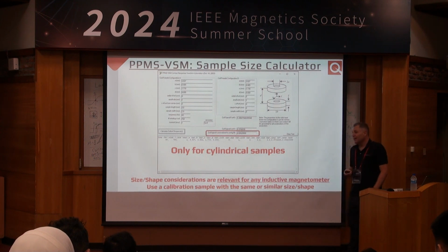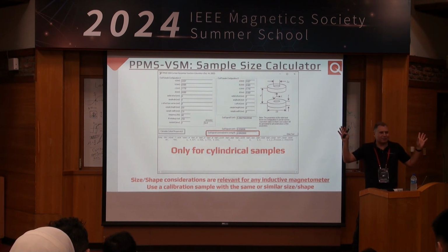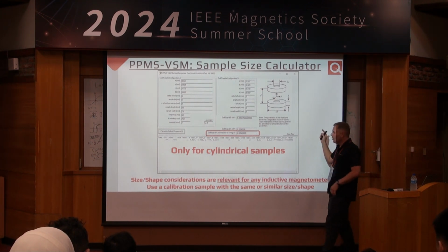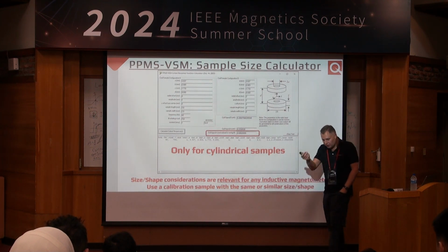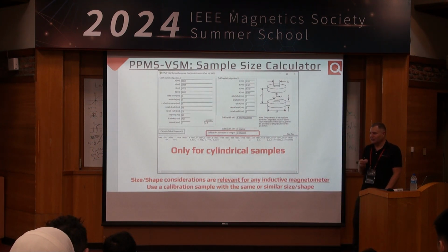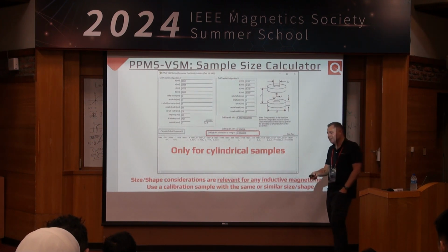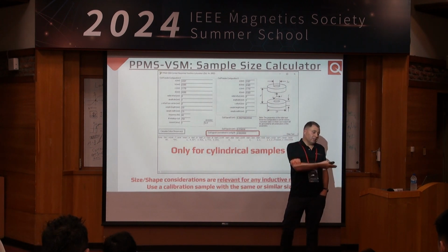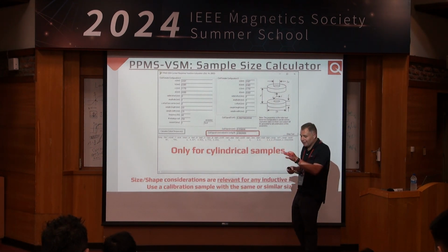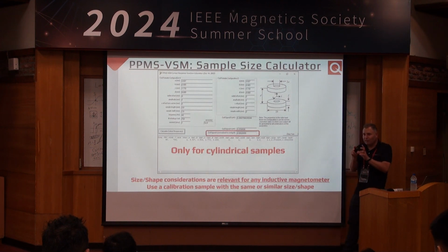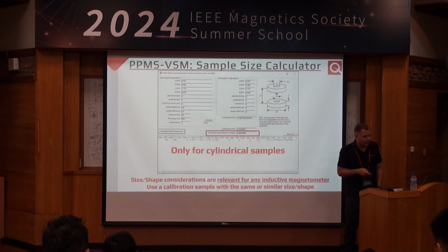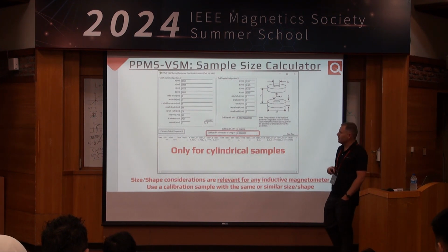These things affect things. Now, if you're like me, when I was a graduate student, all of my hysteresis loops, I just normalized plus minus 1. I didn't care, right? And I understand that's most of you as well. But if you actually care, you have to take these things into account. Let's say you're measuring a thin film, and your advisor says, hey, how thick is that thin film? How do you know? Well, you did X-ray reflectivity, you know the thickness, maybe you did some profilometry. He's like, well, let's also do magnetometry. You go ahead and calculate the saturation moment. You divide by the volume. And it's off. Well, maybe it's because your measurements weren't as accurate as they should have been. So these things need to be taken into account.